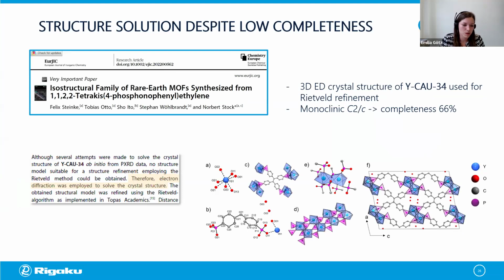Like this MOF paper from Steinke et al., for example. In their case, just the powder pattern was not enough to find a structure model, and they managed to solve the crystal structure of Y-CAU-34, a MOF with rare earth elements in it, with 3D-ED, although only obtaining a completeness of 66% because of its monoclinic structure. However, the completeness didn't matter that much in this case because they then refined the model on the powder data with the Rietveld algorithm and managed to get a nice refined model out of it that way.